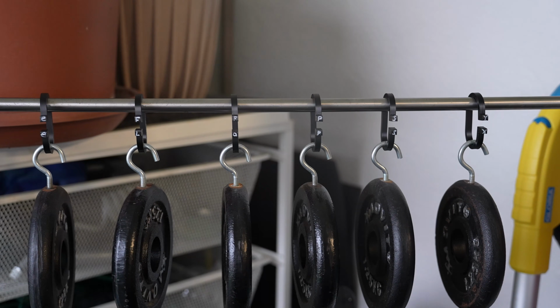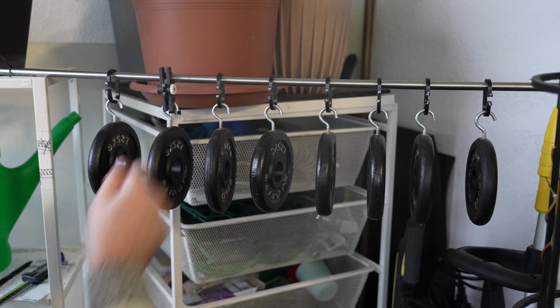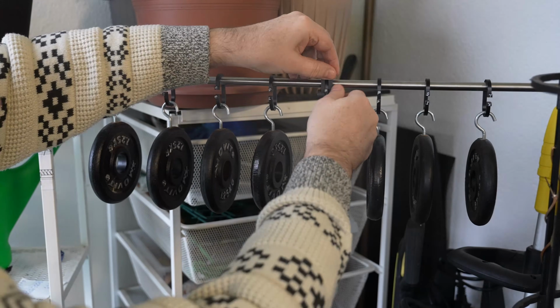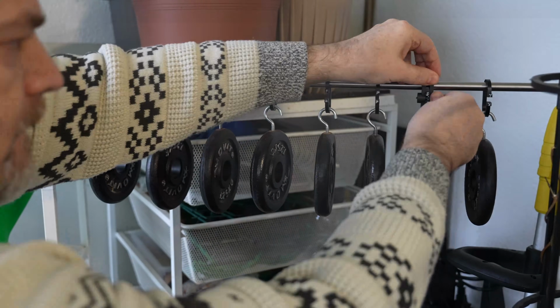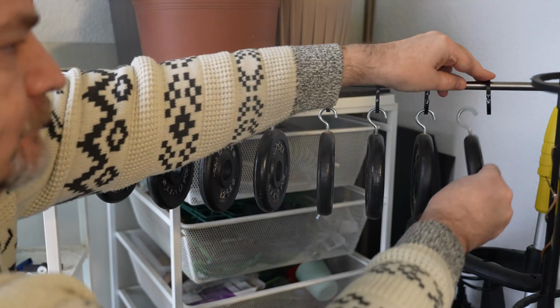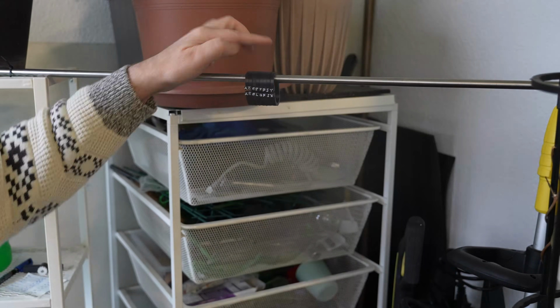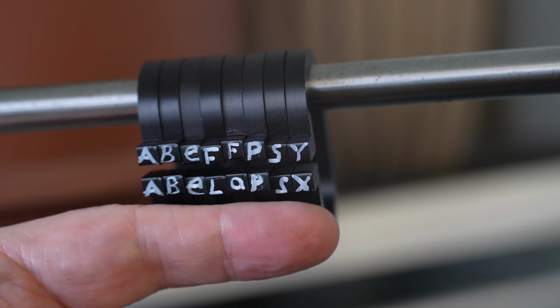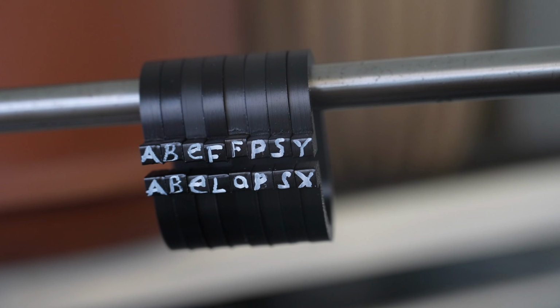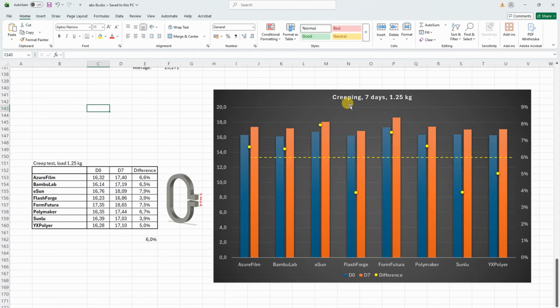And now after 1 week, let's measure them again. Again a time-lapse video. If you didn't see this measuring earlier, I'm locking the position for more accurate measuring, and I'm measuring the distance between 2 reference surfaces. And visually their permanent deformation is very similar. I think low creeping is important property of ABS materials, one of the reasons why we want to go with the ABS instead of the PLA or PETG.